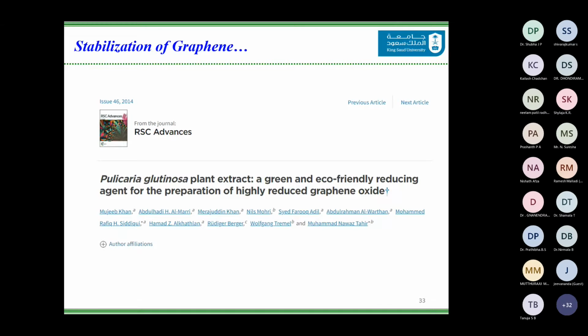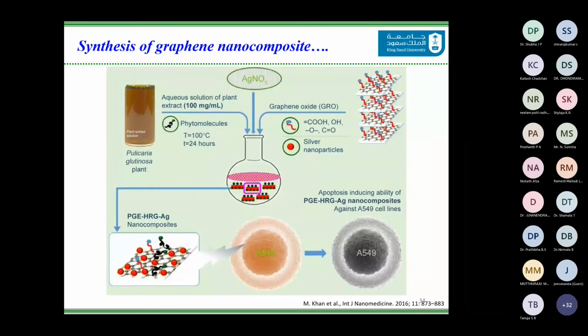Moving ahead, as I told you, my previous work was dealing with reduction of graphene. Now here, what we did was we took graphene oxide as well as a metal salt, and we combined them to make a graphene metal nanocomposite. In this case, we used Pulicaria glutinosa as the plant extract source, and graphene oxide was obtained by oxidation using Hummers' method, and we combined these three with the metal salt in situ, and we got amazing results.